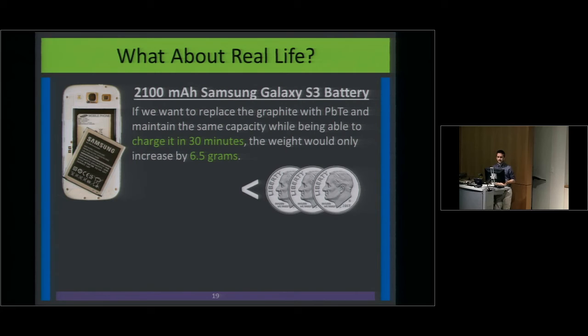So what if we want to put this in an actual battery? I have a Samsung Galaxy S3, it's got 2100 milliamp hour capacity. If I wanted to take that battery and replace all the graphite in it with my lead telluride material, I could charge and discharge it in 30 minutes, and the weight would only increase by about 6.5 grams. That would be like taping 3 dimes to the back of my battery, which I think is a pretty good trade-off if I can charge it in 30 minutes.